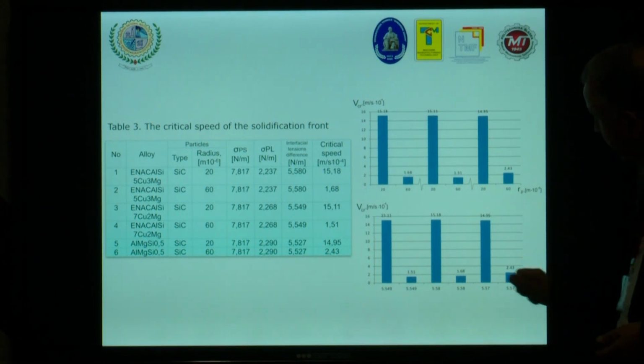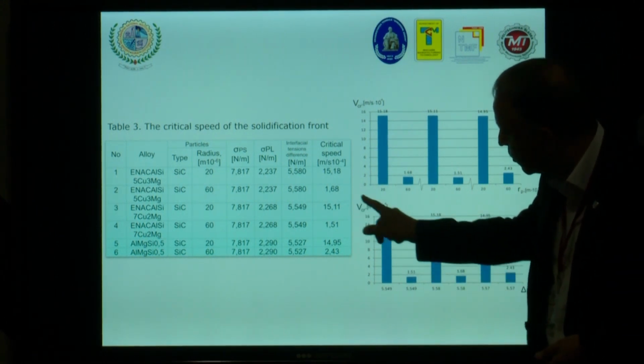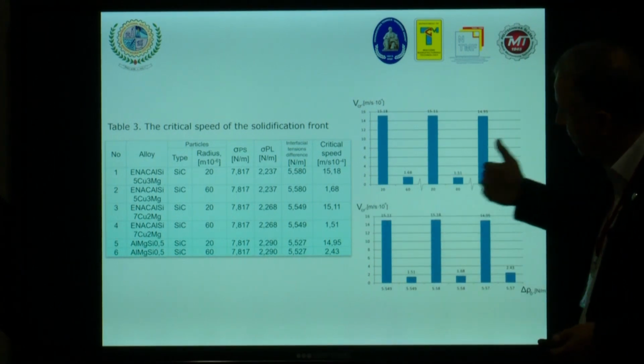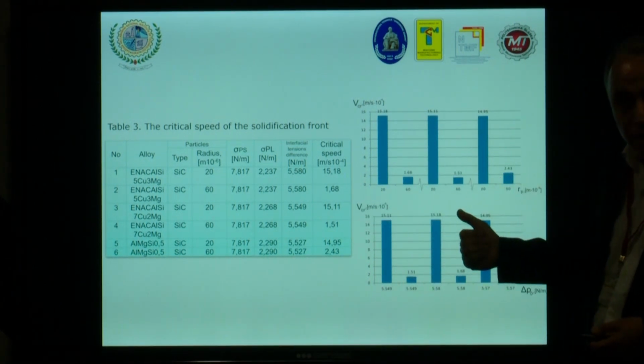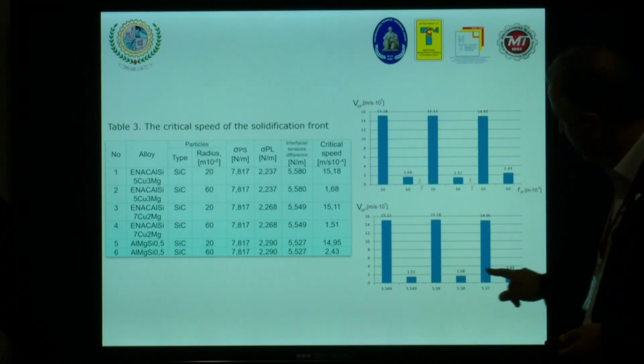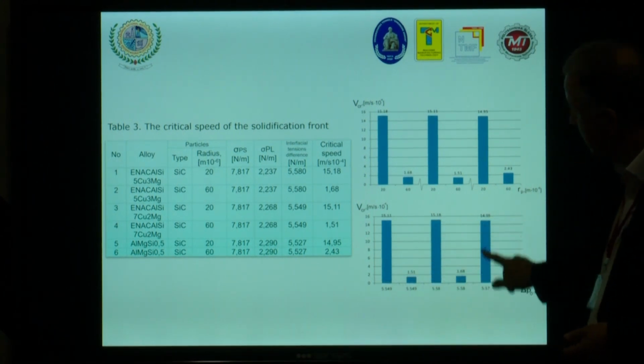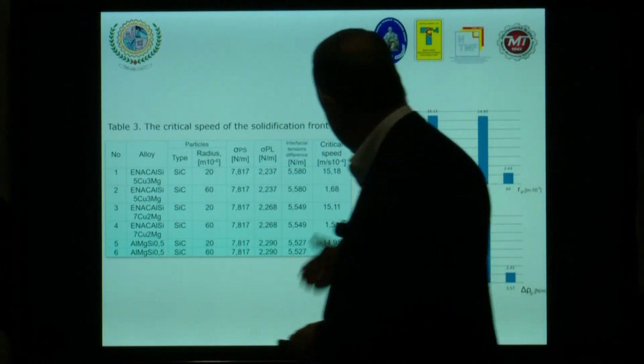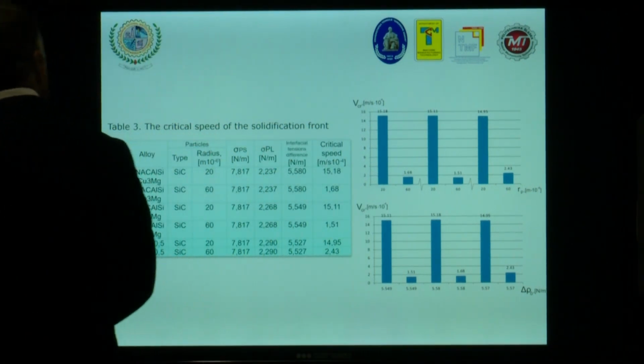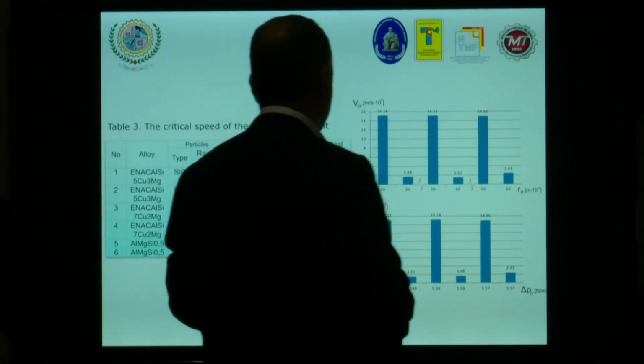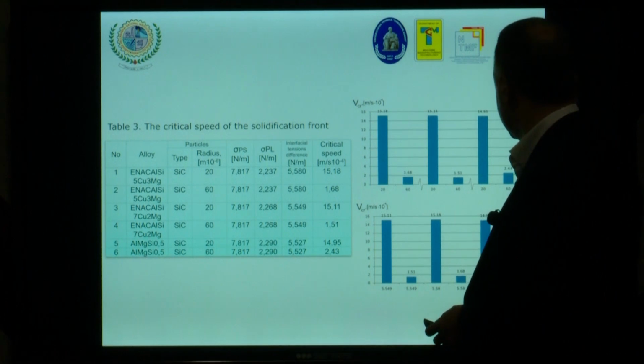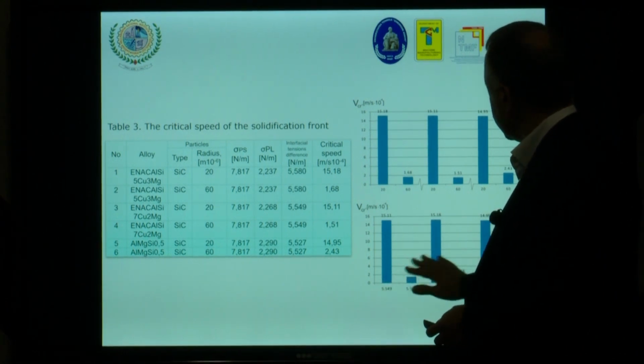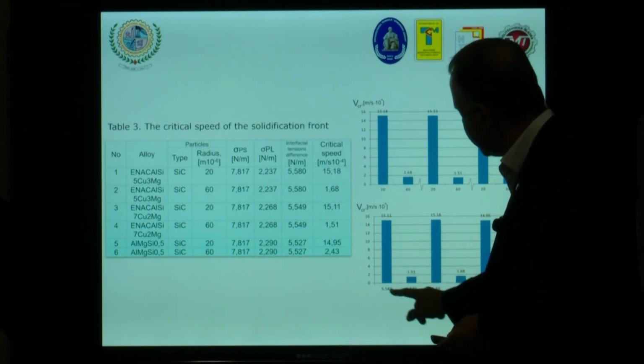If you want to go further, also the variation of critical speed is a function of density. You can see also that the highest is in case of the density being more or less the same in case of the first alloy that we used.